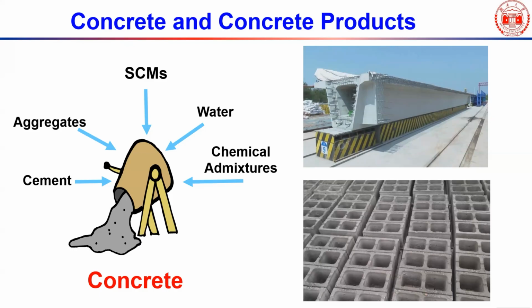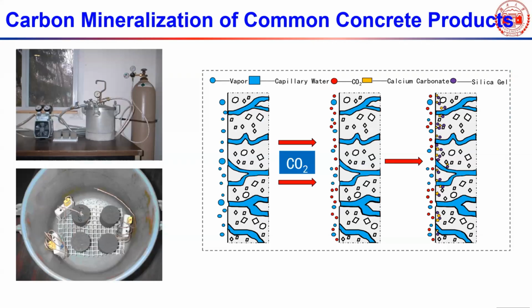Initially, when I started working on this project, I thought a block looks very porous and rough, so CO2 can go inside very easily, but actually it doesn't. Because in order to get a whole piece of compacted product, they have to use a proper water-to-cement ratio and compaction pressure to ensure all the voids within the product are filled with water. Otherwise, it will fall apart. So in that case, CO2 still cannot go inside.